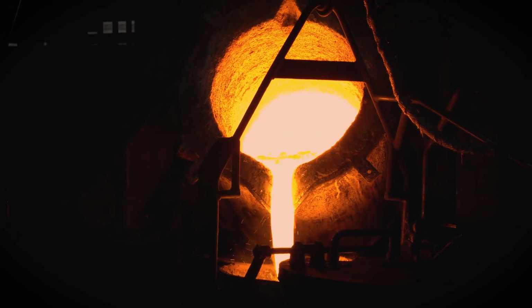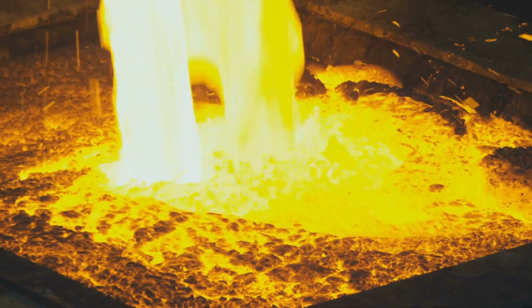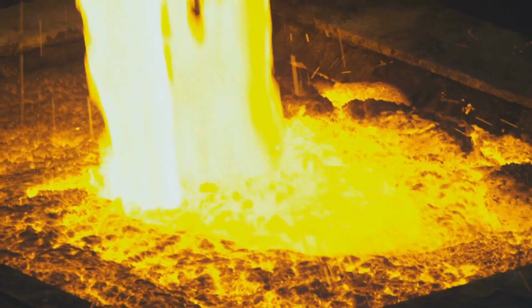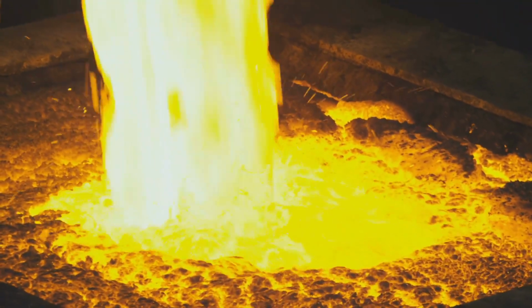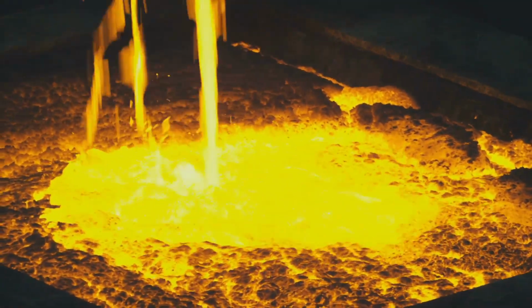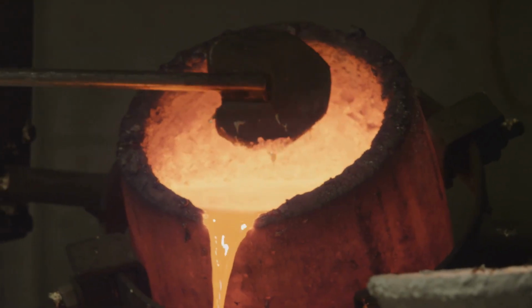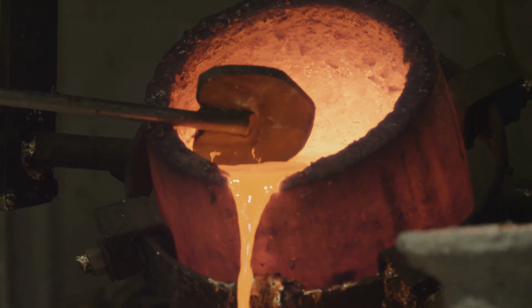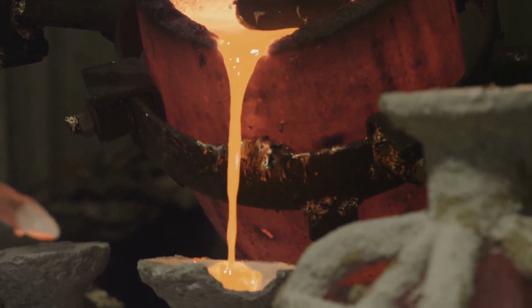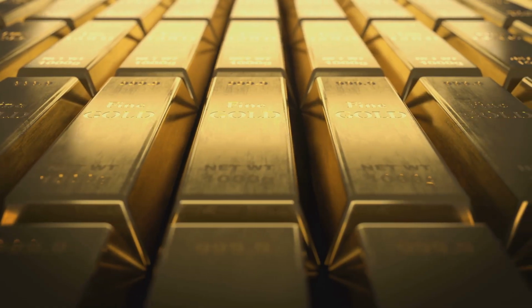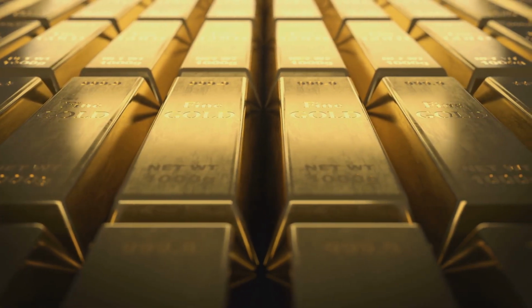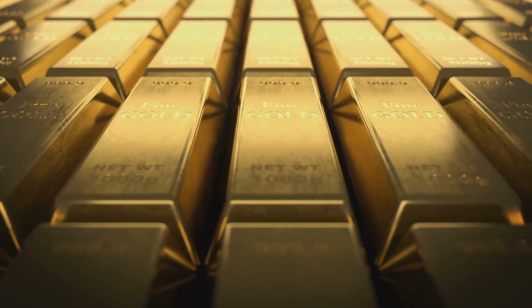Fluxes help form slag and separate impurities. At over 1,000 degrees Celsius, gold melts and, being dense, sinks beneath a floating slag layer. This is the most dramatic moment, the pour, liquid fire cast into ingot molds. Mine site bars are doré, French for gilded, an alloy rich in gold and silver.